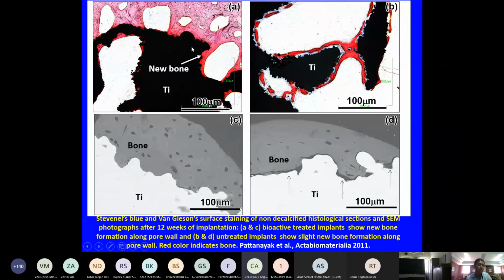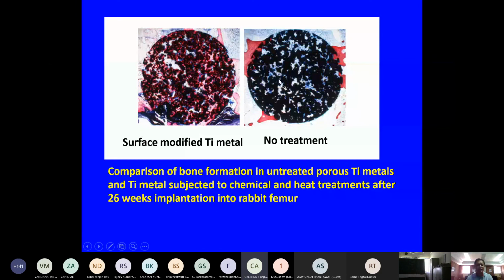But when we modify the surface using the concept of nanotechnology, with a nanostructure layer, you can see in the left hand side image that bone formation has happened directly, adhering to the implant or metal surface. This indicates that the implant fixation is very firm, and if we use this surface modification after 3D printing, it will lead to tight implant fixation or osseointegration on the surface modified 3D printed titanium sample. Here is another classic example of surface modified titanium metal with a nanostructure layer. The red color is the new bone formation, and without any surface modification there is very little bone formation, but the surface modification accelerates osseointegration or bone formation on the implant surface.